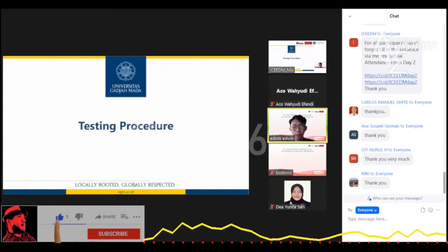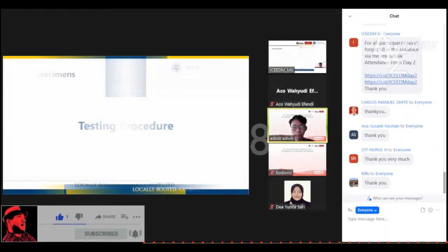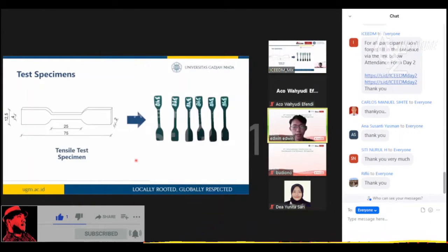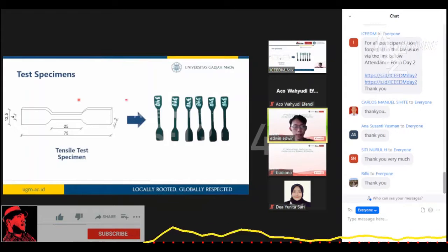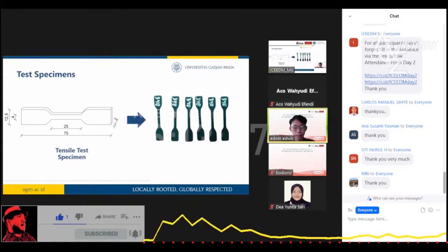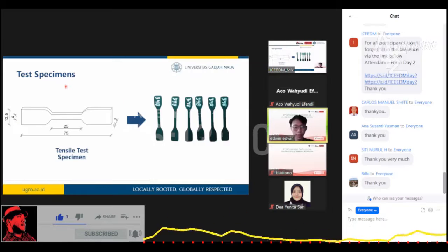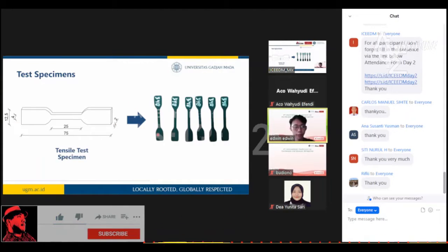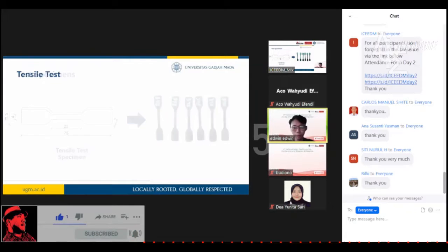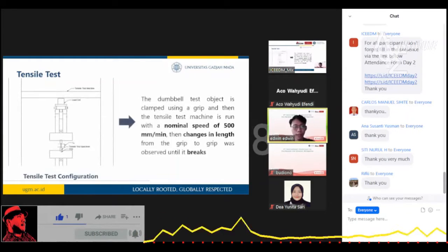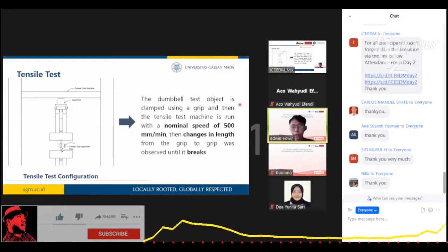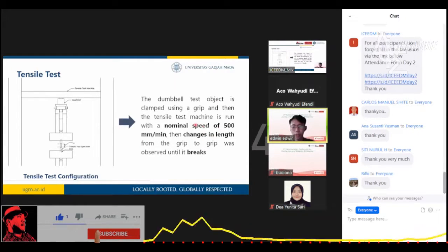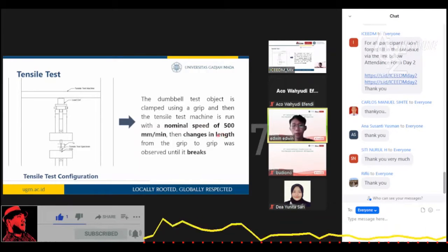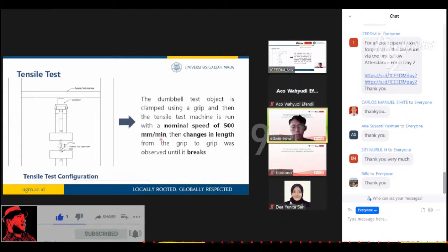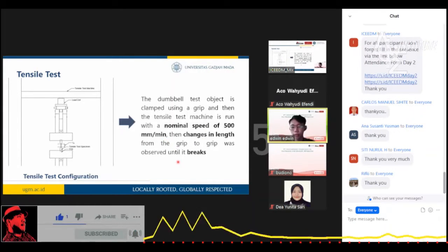Next is the testing procedure. First is the tensile test, and this is the specimen used for the tensile test. Dumbbell-shaped test specimens were used for tensile test with dimension as shown in the figure. And this is the tensile test configuration. The dumbbell test object was clamped using a grip, and the machine will operate with a nominal speed of 500 millimeters per minute, and the changes in length from grip to grip was observed until the test object breaks.